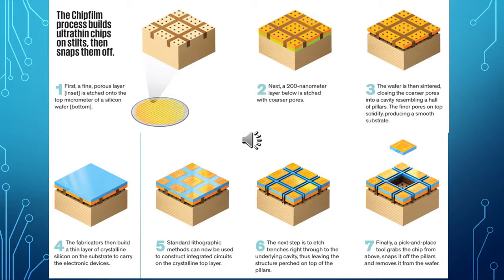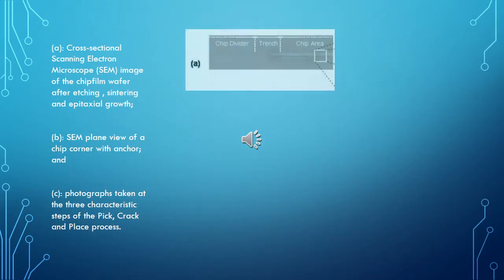The ChipFilm wafers are roughly 20 micrometers thick, which is sufficiently thick for leaving them unsupported, yet thin enough to be able to expose them to bending tests. In part A of this figure here, we can see the cross-sectional scanning electron microscope image of the ChipFilm wafer after etching, sintering, and epitaxial growth.